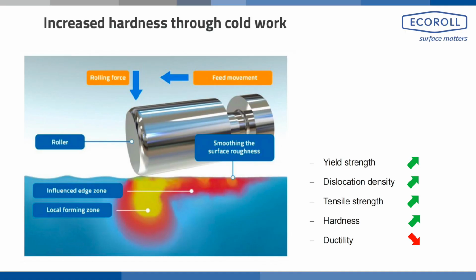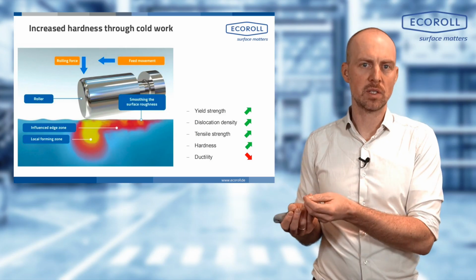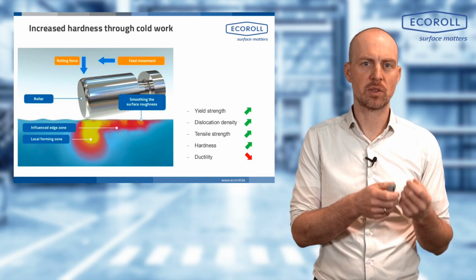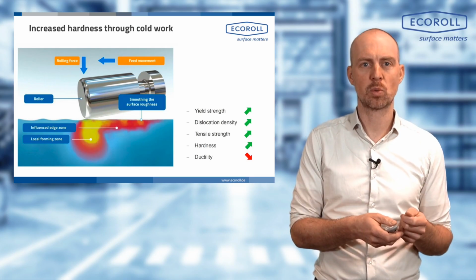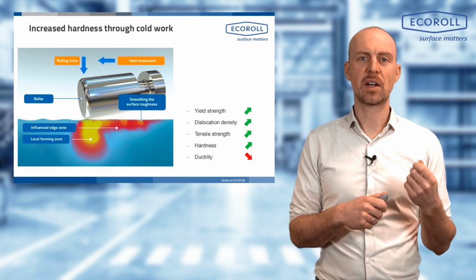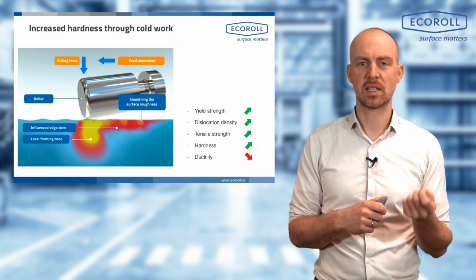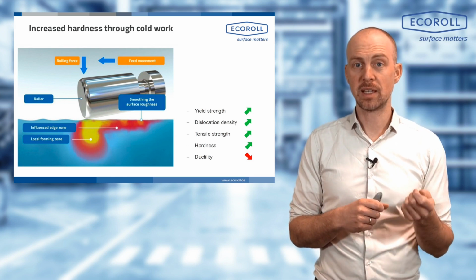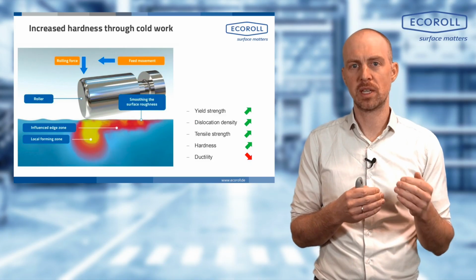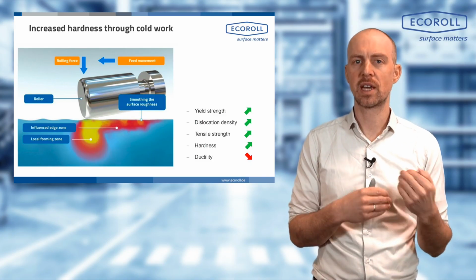An alternative process is deep rolling. In deep rolling, a mechanical roller or a ball, some kind of rolling element, is pressed onto the surface of a component. And as it rolls there, it creates plastic deformation, reduces the surface roughness, introduces residual compressive stress, and, this is the crucial point here, also creates work hardening by increasing the dislocation density. And that leads to the hardness of my component being increased locally in the near surface area.